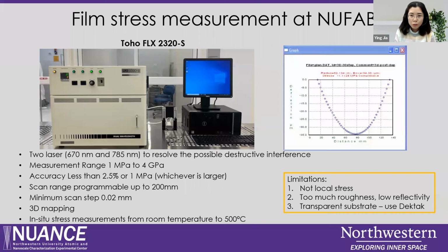But some users come with a spin-coated film of nanoparticles, and those particles can be big and very rough, and this could be a problem. So it really depends on how rough. Generally, roughness less than 10 nanometers is fine. Okay, I see. Thank you.